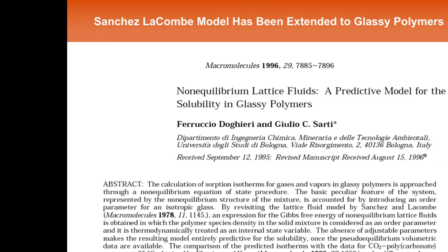If you cool very slowly, so you give the molecules maximum chance to reorganize before they go through this glass transition where long-range molecular motion is effectively frozen out, then you wind up at a lower specific volume, that is at a higher density. And so if you cool the material slowly from a temperature above the glass transition temperature to below the Tg, you can wind up in a more dense state than if you cool it very rapidly. And so these are examples where below the Tg, this material at a given temperature and at ambient pressure has two values of the specific volume, depending on how rapidly or slowly it was cooled. And if you vary that cooling rate between these two values, you'd get a whole family of curves, and the density could be anywhere between these two limits.